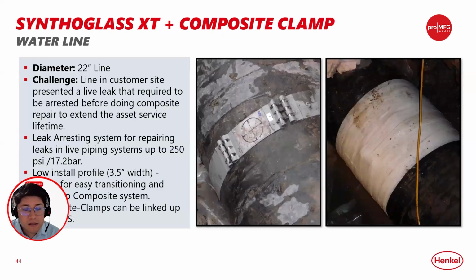Then, as we already mentioned, and as you have seen in the live demo that just helped us, we have a combination of not only the composite repair solutions, but also the live leak sealing solution that we require to then apply the composite repairs. So as you can see, this was also a local case where we utilized the composite clamp to arrest the leak on a 22-inch line, and then we re-strengthened to extend the service lifetime of this pipe using our Synthoglass XT product, as you can see on the right picture. So we arrest the leak, then we re-strengthen using our composite material.